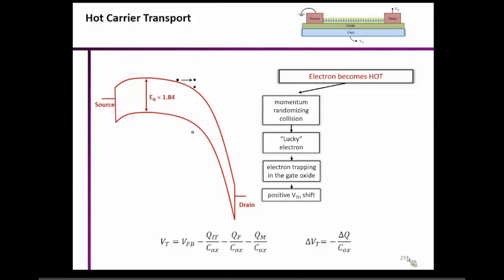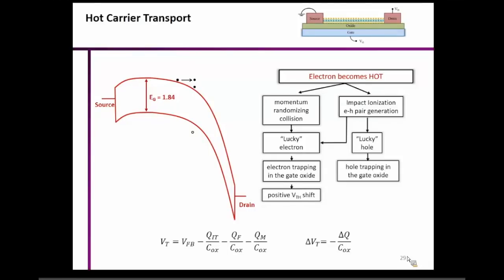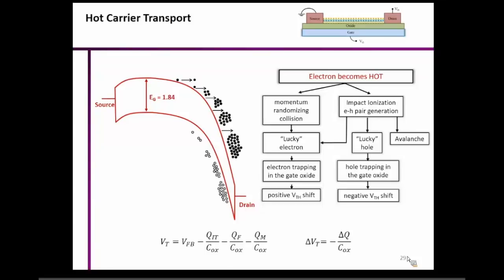Okay. The other phenomenon that could happen is that it collides with the lattice and creates a new electron hole pair. Now the electron from the newly created pair could again become lucky, and it could go through the same process and again get injected into the oxide. But the same thing could also happen with the holes. The holes could also become lucky and eventually get trapped into the oxide. But in this case, we'll get a negative threshold voltage shift. So the threshold voltage shift points to the direction of what the actual phenomenon is, right? And the third alternative is that they don't do anything, they just keep multiplying, and in that case we'll have